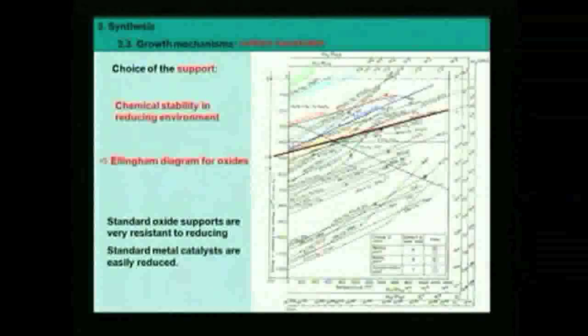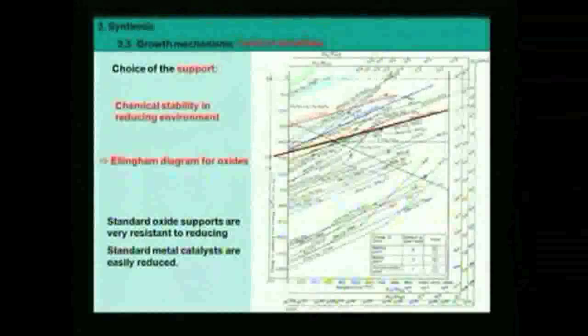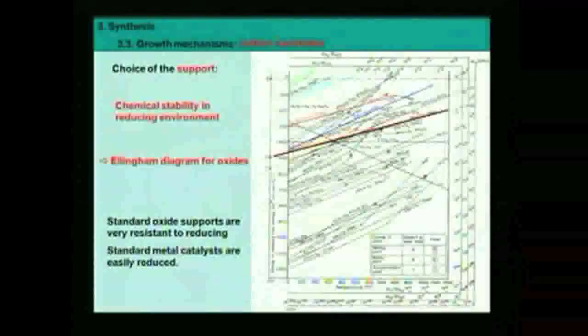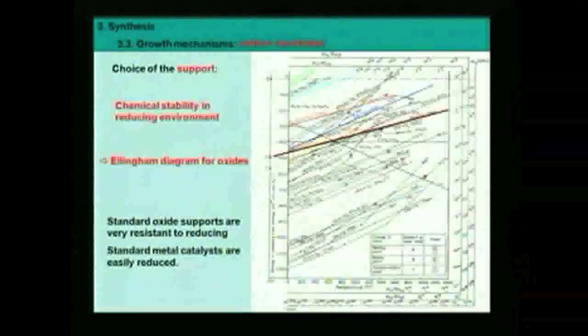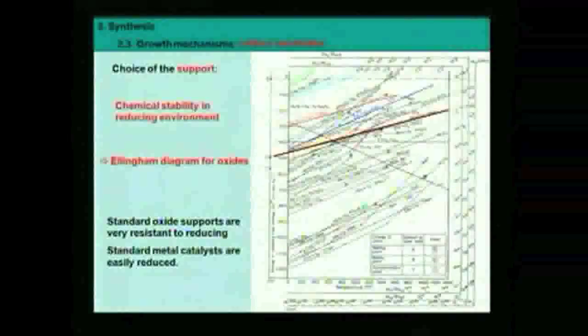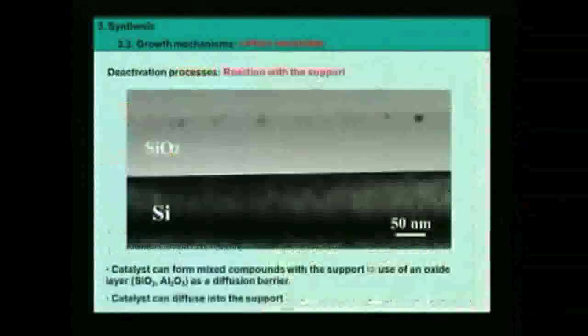Okay, so from this diagram we confirm that we need very resistant oxide supports like silicon oxide, aluminum oxide, magnesium oxide, titanium oxides. Those are good supports. And metal catalysts in standard growth conditions where there is a lot of hydrogen will be reduced. Most of them will be reduced.